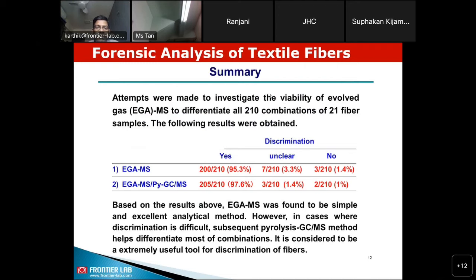Okay, so this was the summary. With the EGA-MS data we were able to differentiate 95% of the samples out of these 210, whereas with the combination of EGA-MS and pyrolysis GCMS, you can go even higher, up to 205 samples. Only a few samples could not be differentiated from the pool. So the combination will be useful when you are not able to do it by one approach of evolved gas analysis.